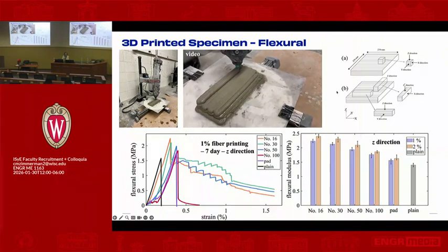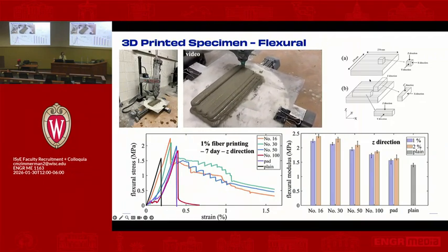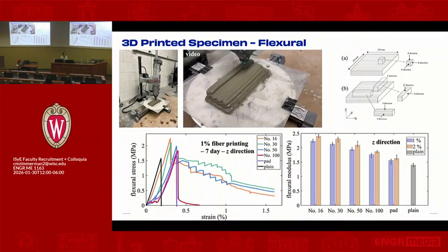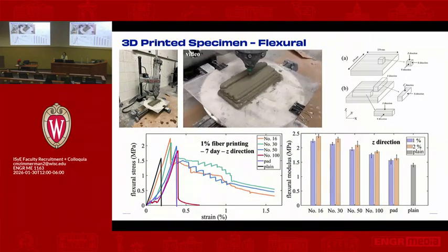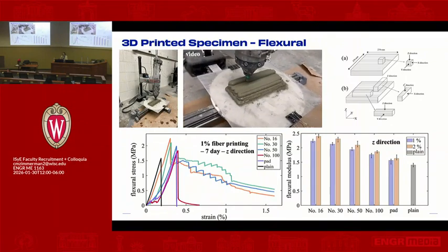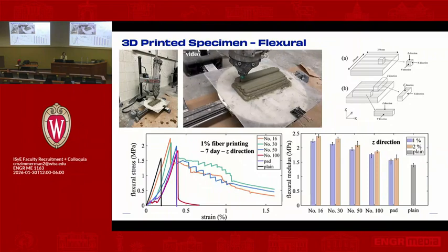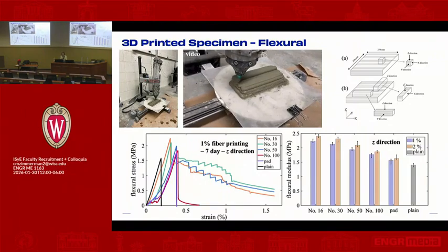And so you can see the samples that we were able to generate, in terms of what we measured. A couple of things that we were measuring were flexural stress and the flexural modulus. The different categories that you're seeing here are basically the diameter of those fibers. And remember, these are batches that come in a bag. We don't have a whole lot of control over them. We're just using them first without any milling, any ball milling or anything, just to see what we're actually getting. So you get an average, where some of them would have larger diameters, and others would be longer. And you can see, of course, that with the higher amount of fibers, we get a better modulus.